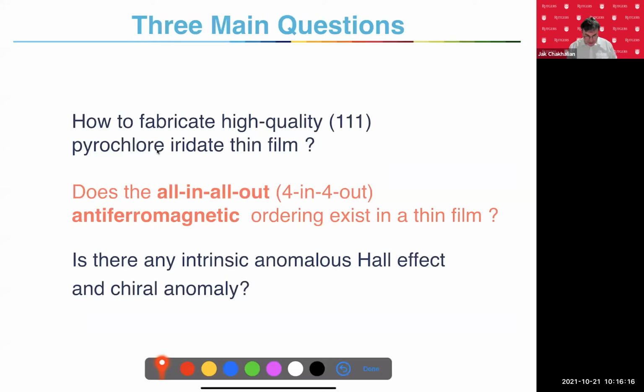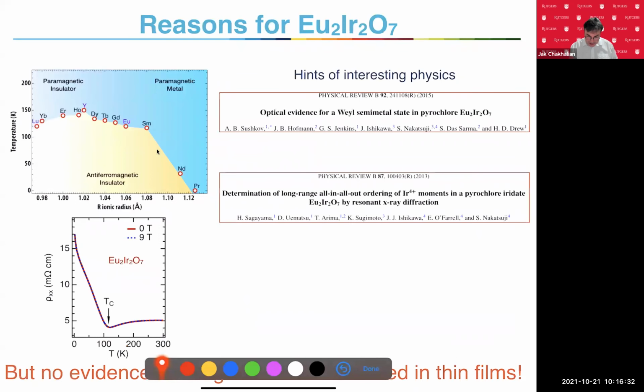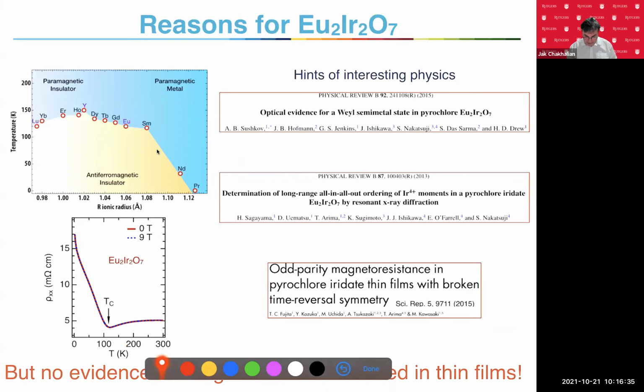With this material, the next question is, okay, you have an ultra thin film. Do you have this unique magnetic order? Because that's what makes these Weyl fermions inside. Once the magnetic order appears, the Weyl fermions appear. I'm just showing that lots of papers have been published about this. And then you ask, among the hundreds of papers published, is there any evidence for magnetic order? And the shocking thing, nobody measured it. We don't understand why. Either people tried and couldn't see it, but no one reported this. So that was really strange to us.